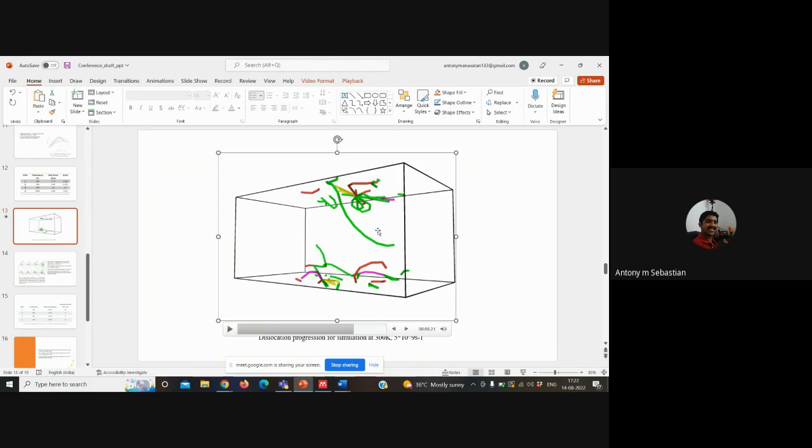Tangling of dislocation pileup, and then we observe partial dislocations too. So for this particular study, it's the 100 orientation, the normal orientation, and that's how we observe this certain dislocation progression. It will also vary according to the grain orientations, but we have not dealt with that in the study. This is just a simplified case where a 100 orientation is used and the stress is applied along it, and then we study the deformation behavior of it.